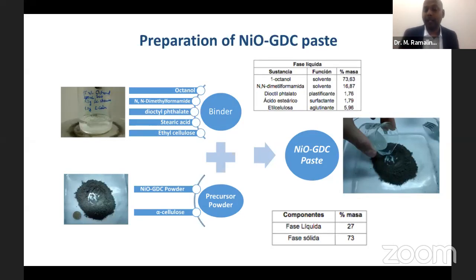So it's more important to have crack-free tubes, because we are going to sinter the tubes, and at the same time our aim is a porous tube. So it needs to be porous, at the same time without cracks, and fine shaped tubes. So the paste plays a big role in fabricating the ceramic anodes, which will be used for ceramic fuel cells. So this paste we have formulated.